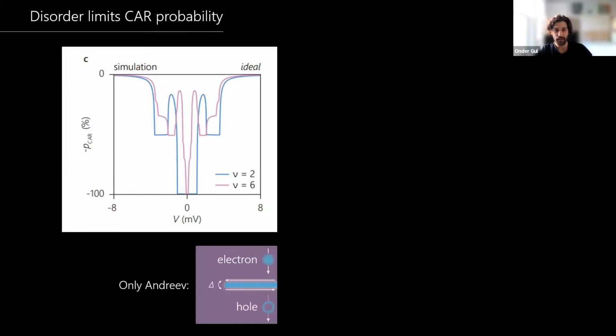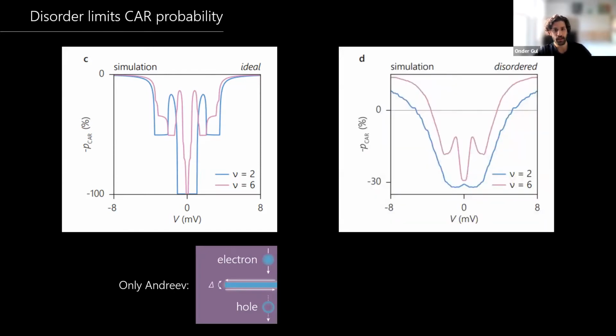Some remarks may be in order related to the low CAR probabilities. In our experiments, CAR is at most 10%, and integer fillings show around 1% probability. In the ideal case, the CAR probability is 100%, unity, basically related to topological constraints. Okay, this is basically the topological superconductivity explanation. We have included a disordered pairing potential in our calculations. Basically, the only difference between the simulation of the ideal and the disordered case is a disordered pairing potential. It is similar to the disorder expected in the experimental case. And this reduces CAR probability.